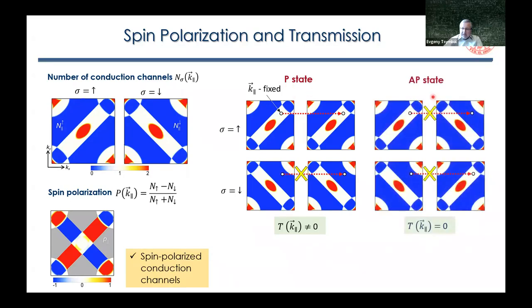If you go to the anti-parallel state, obviously we flip the spin designation in the right electrode. And then while in the left electrode we have some state available, we don't have the state in the right electrode. And for both spin channels, we should have transmission equal to zero. So this is a simple explanation of why we should have higher transmission for the parallel case as compared to the anti-parallel case. And that's driven by the Fermi surface mismatch for the anti-parallel state.